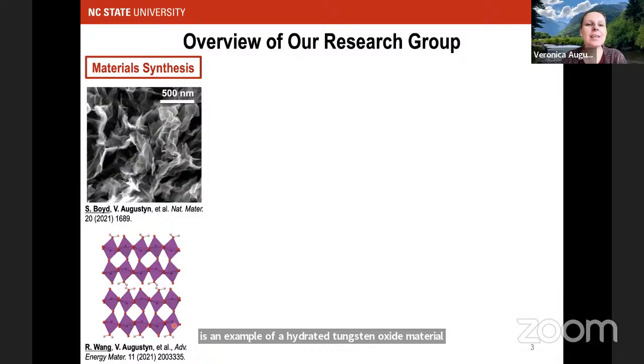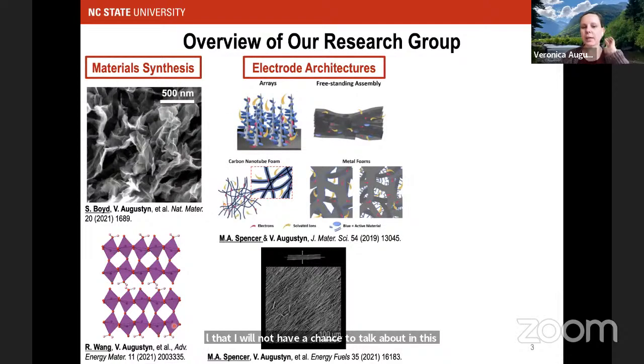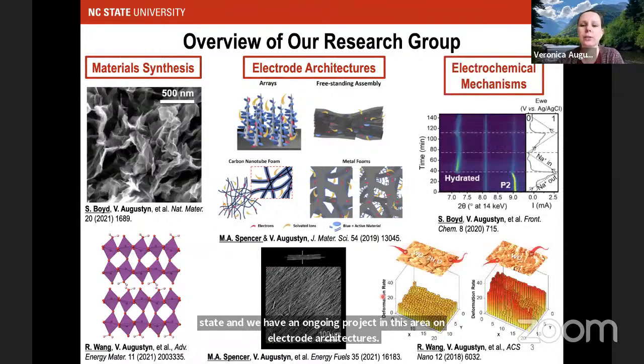about in this presentation. An important component of our work on electrochemistry of materials is, of course, getting them onto an electrode. And that can be as simple as just doing an electrodeposition reaction, as is shown here, where this is grown directly on a conductive substrate. But it can be more complex, especially if you're thinking about energy storage applications where you want high areal capacities or high volumetric capacities, and you start thinking about really optimizing ion and electron transport pathways through both the solid and the liquid state. And we have an ongoing project in this area on electrode architectures. Thick electrode architectures, I should say.